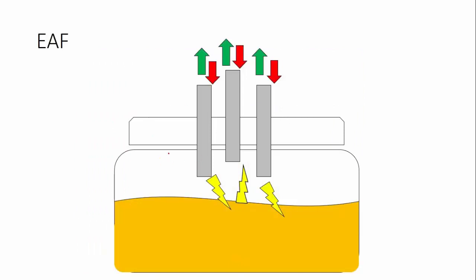Some scrap material goes into the shell like this. This is scrap steel, which can be found in any junkyard. Then the electrodes, which can move up and down, go very near the scrap metal, and since they have a voltage applied to them, they form a short circuit, and that short circuit forms an arc, which can get very, very hot, around 20,000 degrees Celsius. That arc starts to melt the scrap material and forms a little pool of molten steel, along with a little layer of slag, which is the result of all the impurities from the scrap steel.